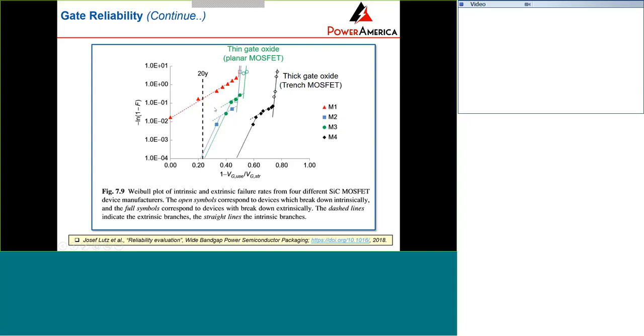If you apply a proper screening approach on this MOSFET, the early failure rate will significantly reduce, as shown in green or yellow. Overall, the planar MOSFET and trench MOSFET show similar early failure distributions, so they have a similar failure rate. The only difference is that the thick oxide fails at a higher voltage, in the trench MOSFET, just because of the thicker gate oxide. Both devices could meet the 20 years of safe operation criteria, as shown in this figure.